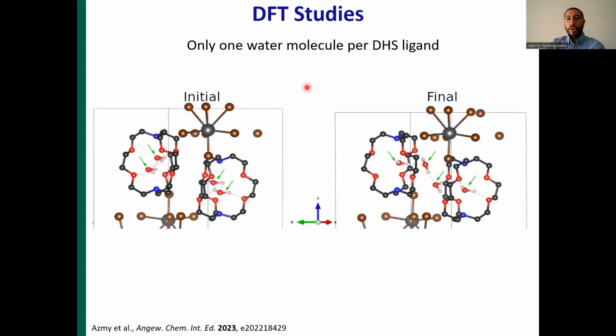We also wanted to identify the number of water molecules that can reside in the structure and in the organic cavities. So this is the initial configuration by adding 2 water molecules per organic ligand. And this is the final configuration of the structure after structural relaxation. Apparently, only 1 water molecule can reside in its ligand, whereas the other 2 molecules were expelled from the cavity. And this is in perfect agreement with the gas sorption studies, where we found that the uptake correlates closely to 1 water molecule per organic ligand.